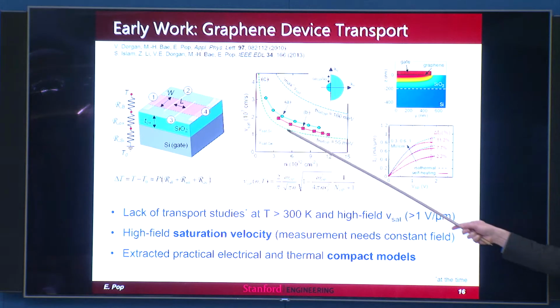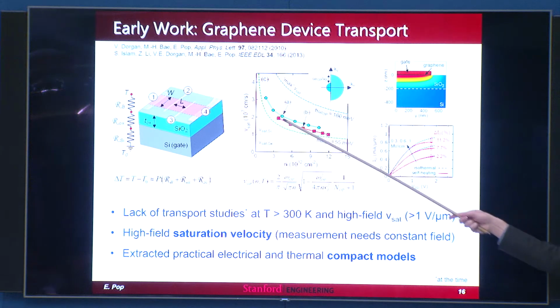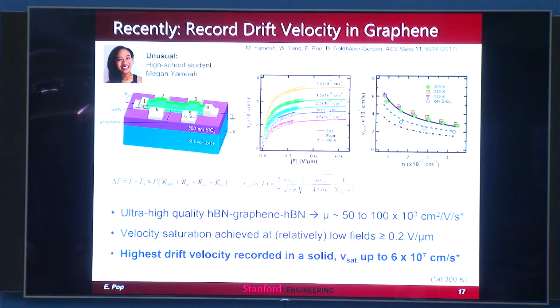You also see that if you're worried about scattering with a substrate, you're actually probably scattering with the SiO2 phonons. And this goes back to that comment I made just a minute ago about remote phonon scattering that you see in these ultra-thin materials. That really is still there, unless you suspend your material. So that's basically what we were doing there. We have a habit of doing modeling work as well. In fact, most of my PhD work was on modeling. So there are obviously a lot of modeling questions or answers provided throughout this talk, with some focus on compact models. But these days, we're also doing molecular dynamics for certain problems. So we really span the range.